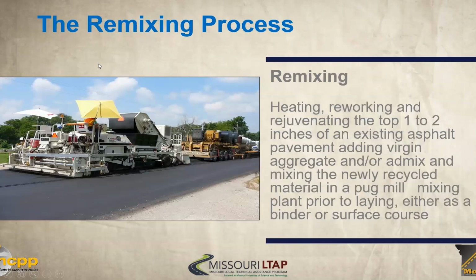So talking about remixing, this is probably getting to be more frequently used than just surface recycling around the country. This is where we're heating, reworking, and rejuvenating the top 1 to 2 inches and adding virgin aggregate, mixing virgin mix in with the newly recycled material in a pug mill, and then laying that, either as a binder or a surface course. And so this is a common type of approach and one that we see.